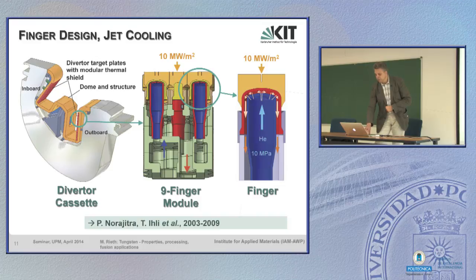This is a single finger, a cooling finger with helium cooling. Helium is pressurized through holes, and then by jet cooling it removes heat from this part in red. This is made of tungsten material. It's a structural application because it's pressurized to about 10 MPa. And on top of it we have a tungsten block of some kind, and its only use is to shield or to protect the cooling structure from the plasma interaction.